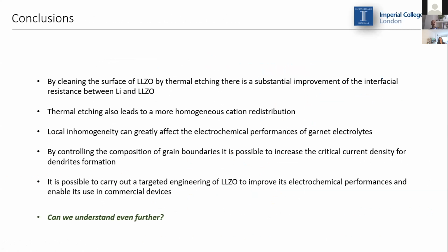To conclude, I want to leave you with some take-home messages. So we saw at the beginning of my presentation, the thermal etching on LLZO pellet leads to a cleaning process, so leads to the removal of lithium carbonate from the surface of the pellet, and we can then achieve a better contact between metallic lithium and solid electrolyte. But we also see how the thermal etching can also lead to a more homogeneous cation redistribution on the surface of our samples.